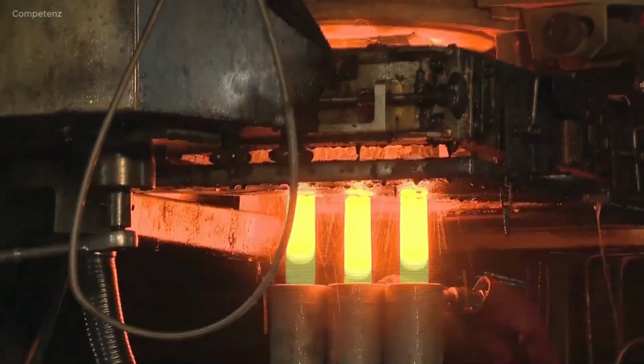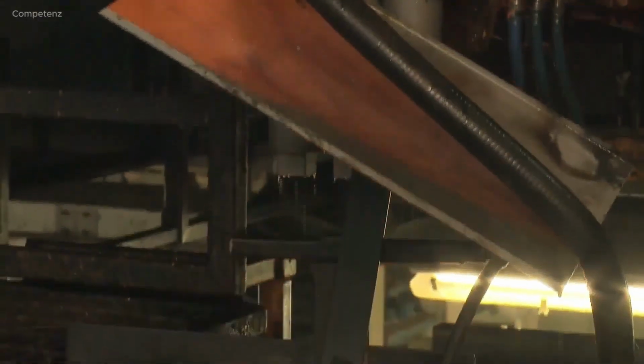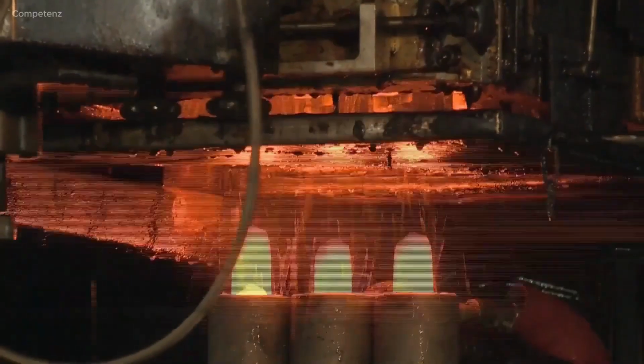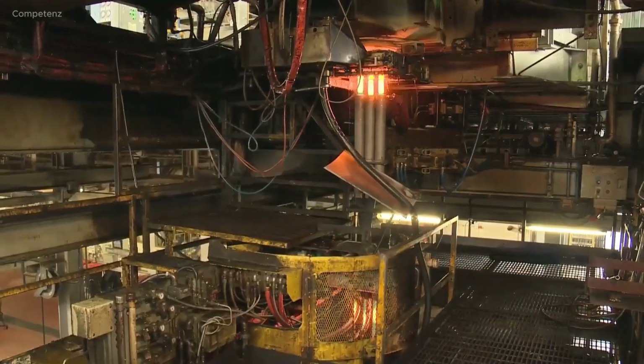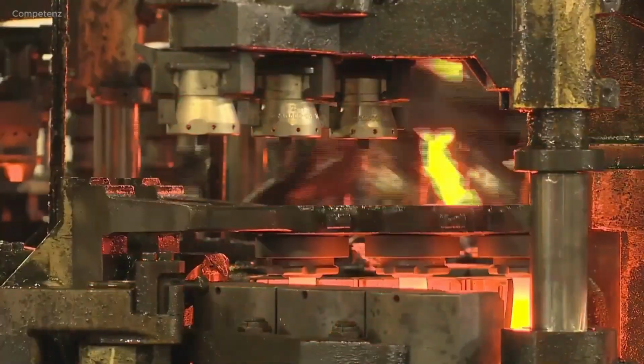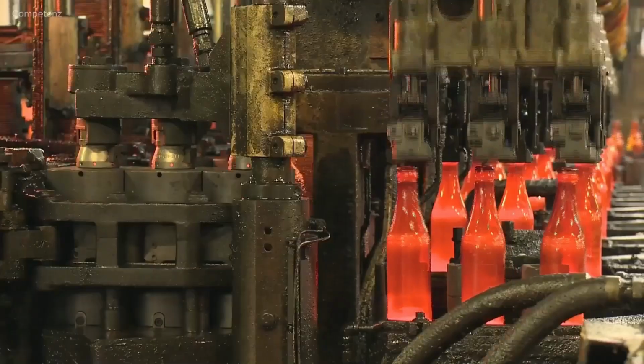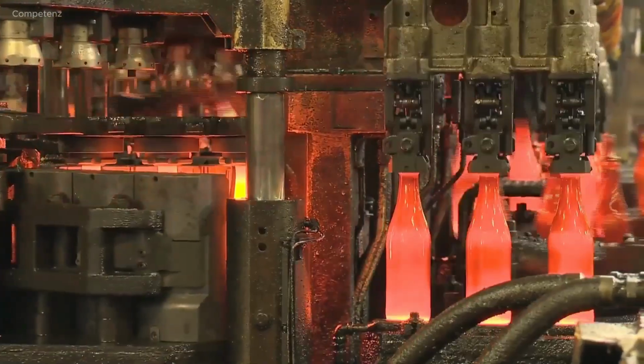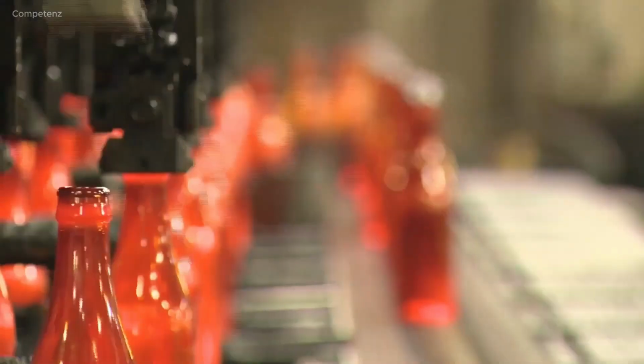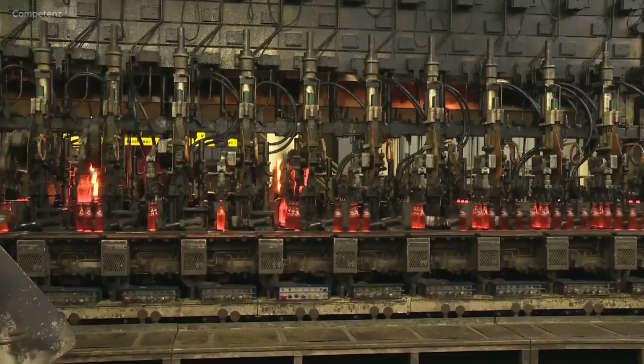The molten glass is then cut into gobs and moved to the blank side of the machine, where it is pressed or blown into a parison. The parison is then transferred to the mold side of the machine, where it is blown into its final shape, like beer or wine bottles or jars. Lubrication is key to smooth operation, using special oil with high graphite content to reduce friction and maintain proper machine temperatures.